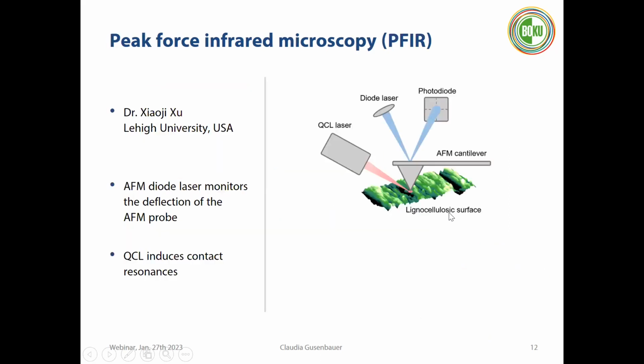And a different method that we applied to also do this chemical mapping is called peak force infrared microscopy. And we did this in cooperation with Xiaoji Xu. He's working at Lehigh University. And he developed this setup where you have this AFM tip scanning your sample, and therefore will deliver us high resolved images of the wood cell wall.